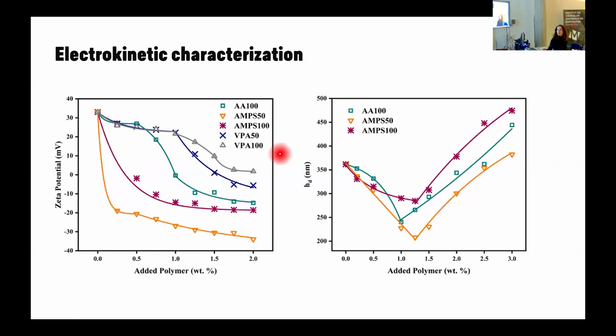So here, for instance, as you see, we have different compositions of polymers that we scan. You can have the homopolymers of these monomers, or you can have the copolymers with acrylic acid. And you can also modify the second monomer in order to obtain a different adsorption behavior. So that is what we do. We need to make sure that it is actually a stable solution. That's why we track the zeta potential.